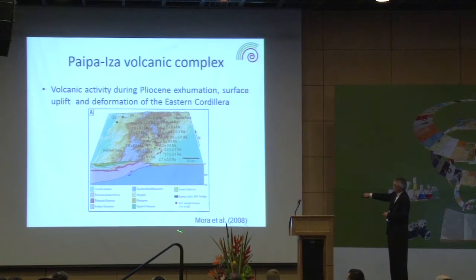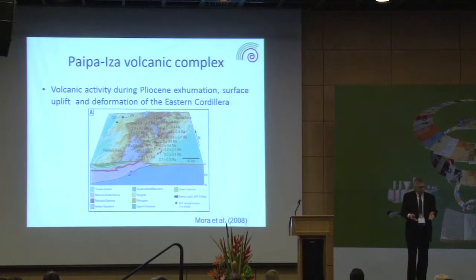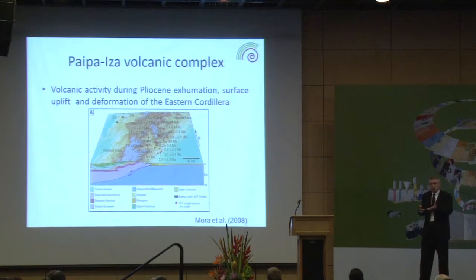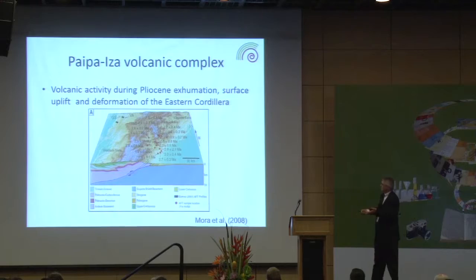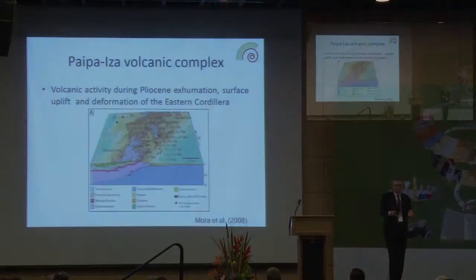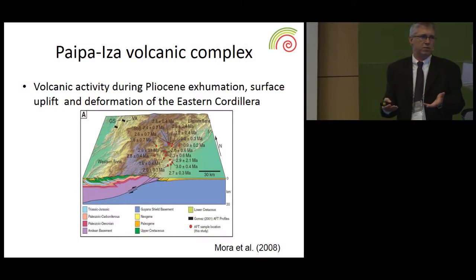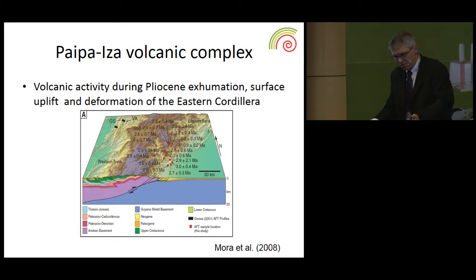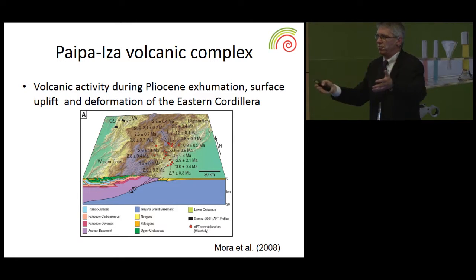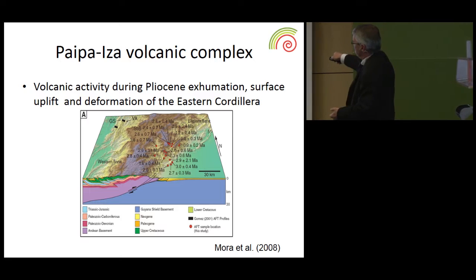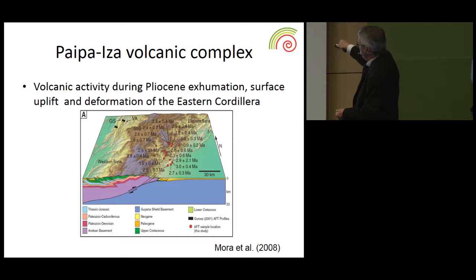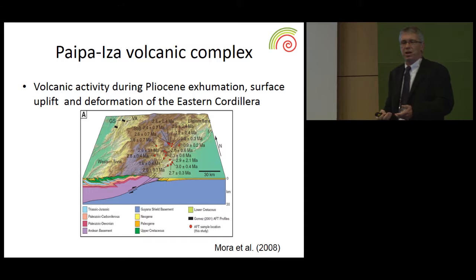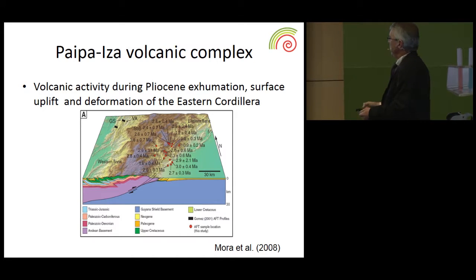And if you look at this work from Andres Mora, I know it's a little bit to the south of where the Paipa-Iza area is, but we can see these are apatite fission track data from surface outcrops, and they indicate that there was exhumation going on in the last 2 to 3 million years. Of course, fission track dating does not give us information about surface uplift directly, but it's a good indication normally, because if we create topography, surface uplift, we start eroding, and that causes exhumation. So it means we had an important phase of exhumation in the Pliocene here.